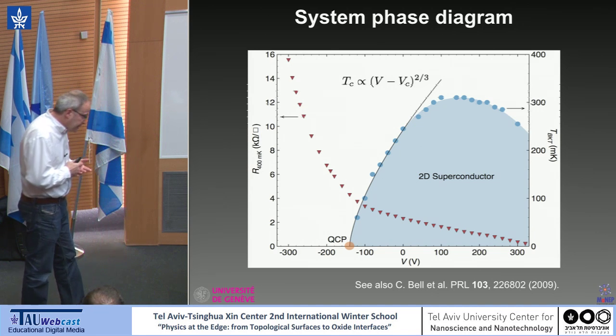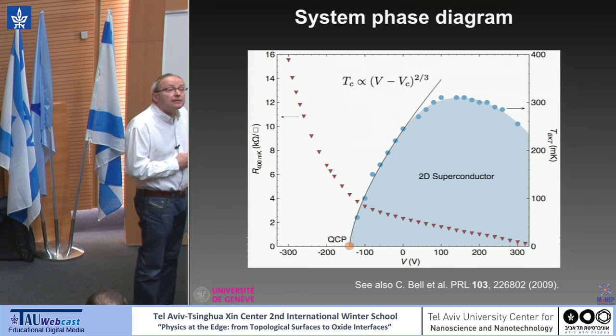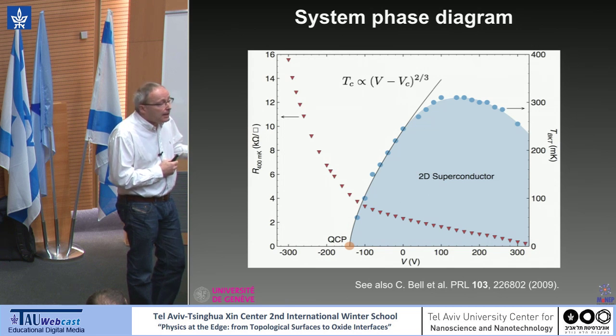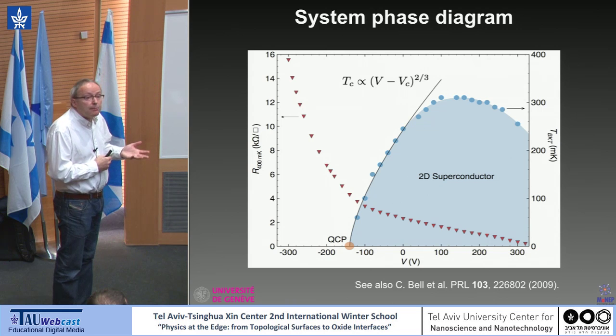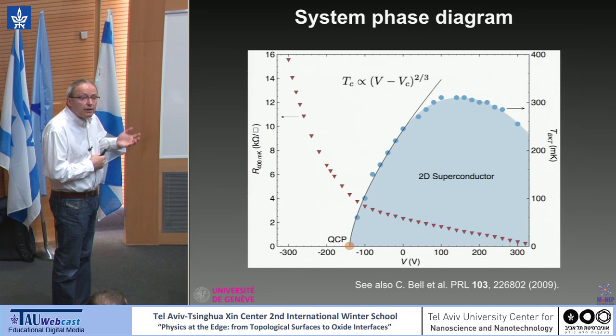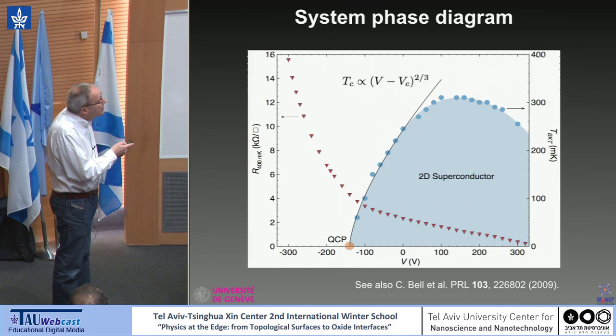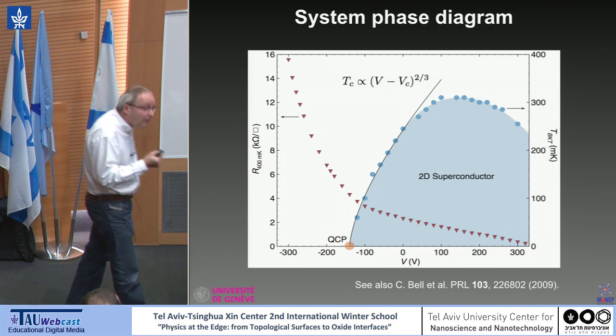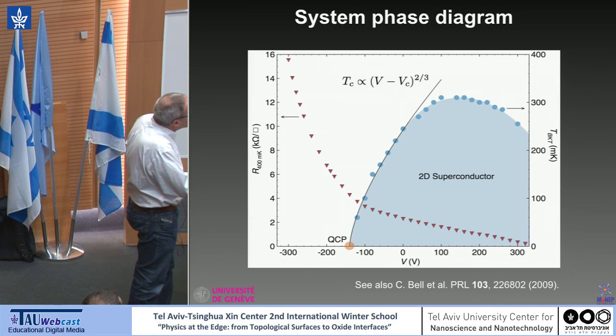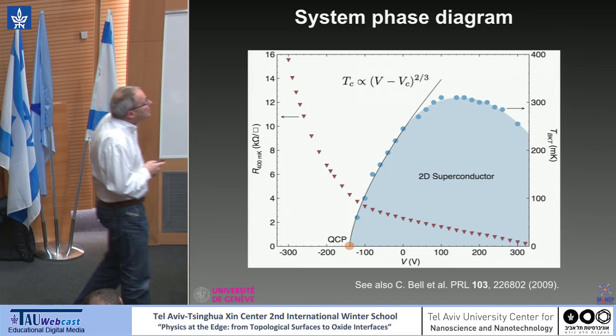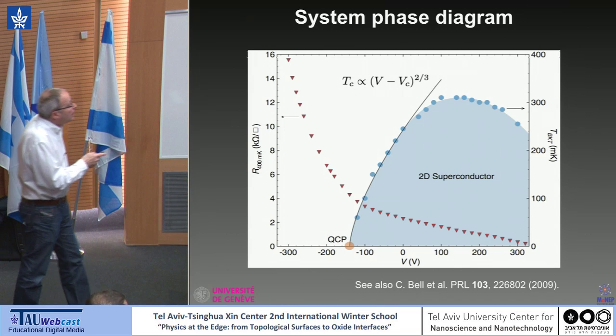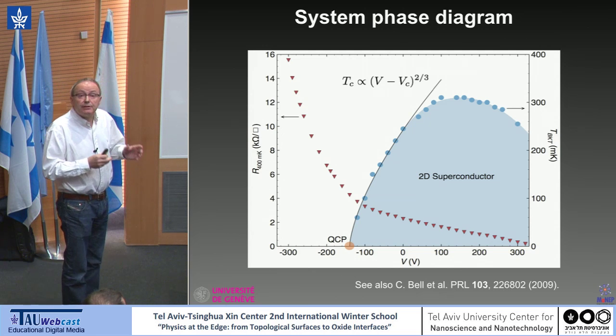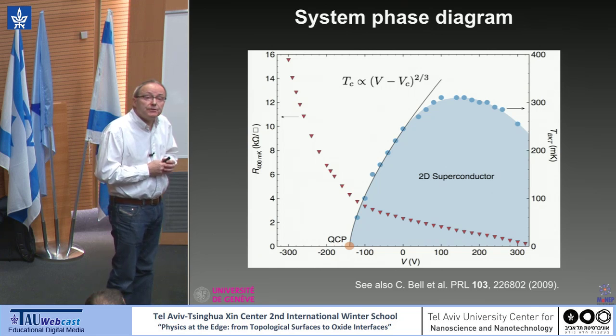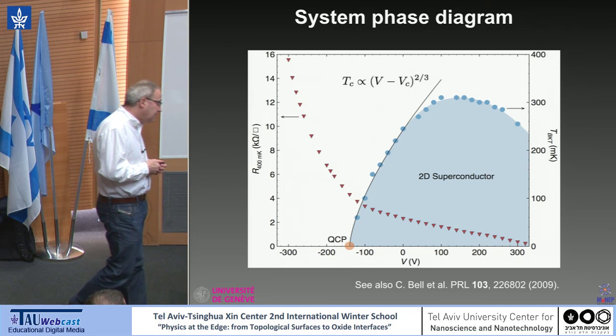And 2/3 is the exponent you expect for a 2+1 D XY quantum phase transition. The XY model is a phase model. So we wondered if this was telling us that the zero resistance state is here controlled by the locking of the phase. In other words, that you have phase fluctuations in this system. I will come back to this a little later. That may seem strange at very low T, but the carrier density is extremely low, so the superfluid stiffness is also extremely low.